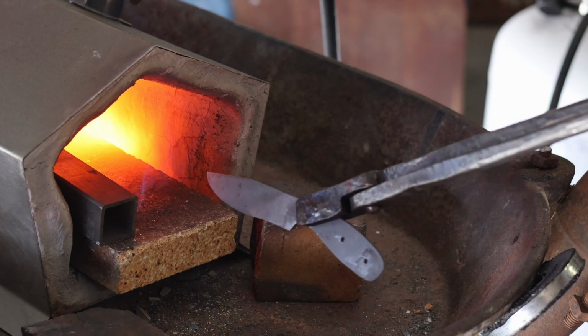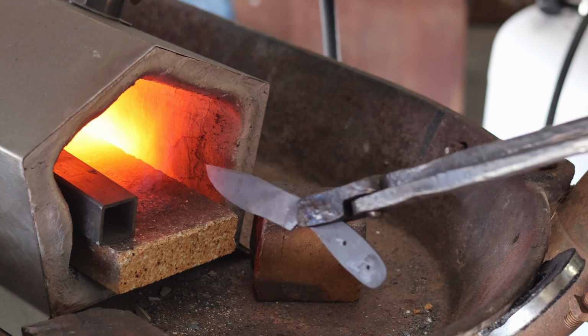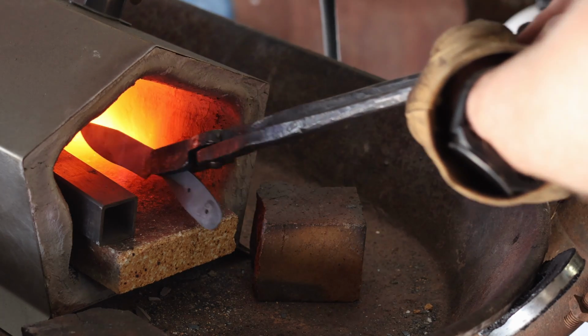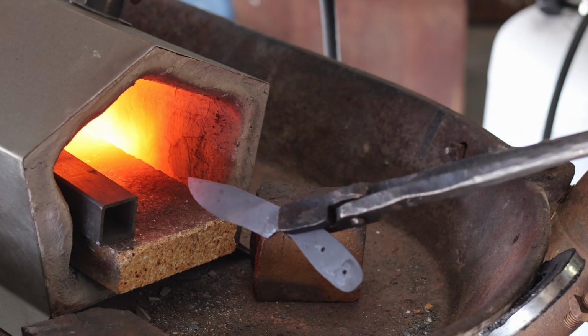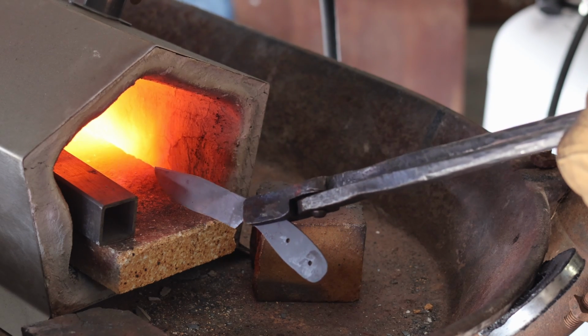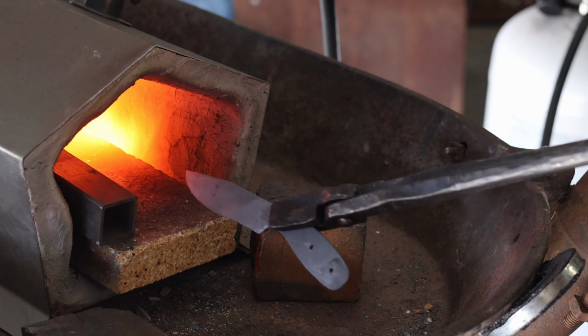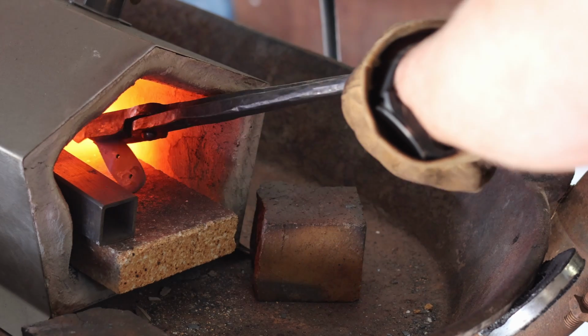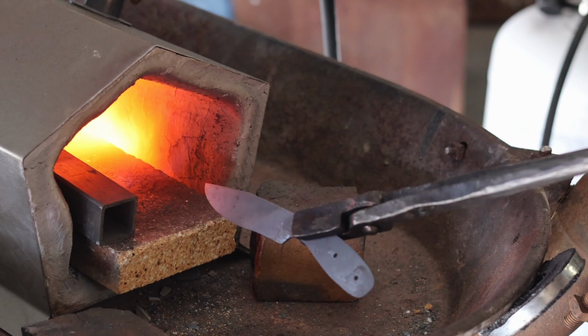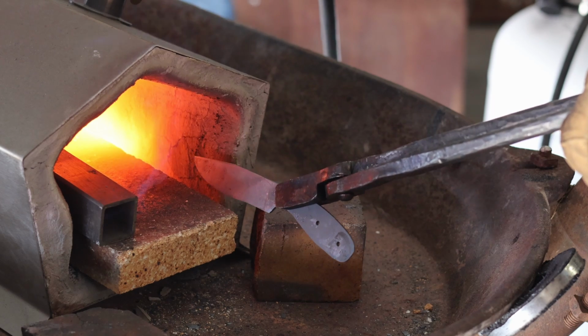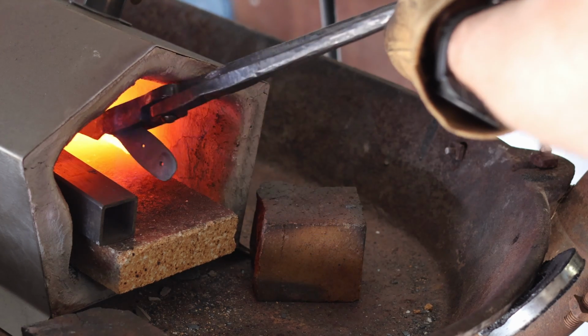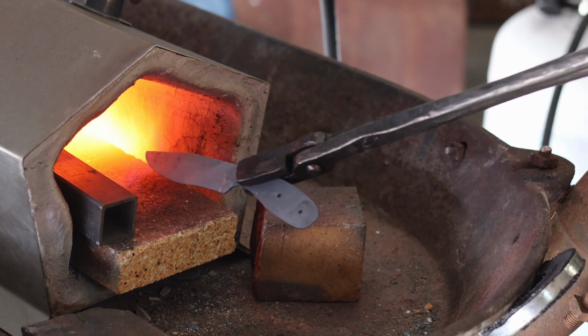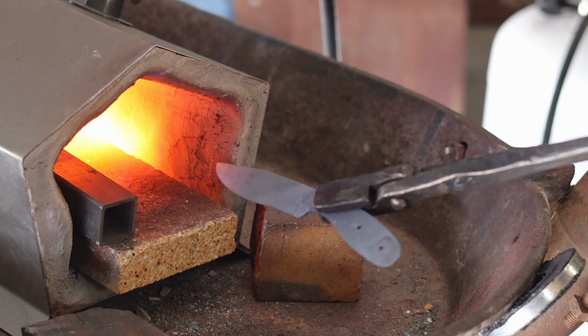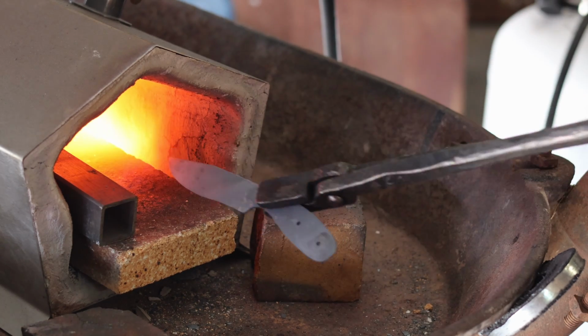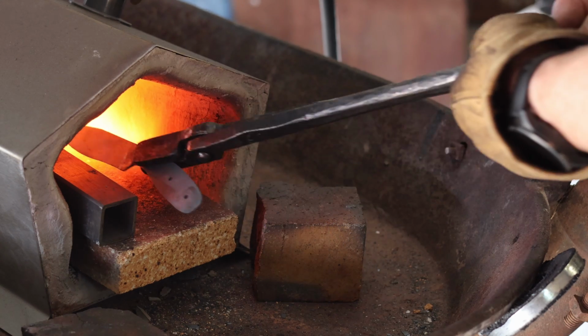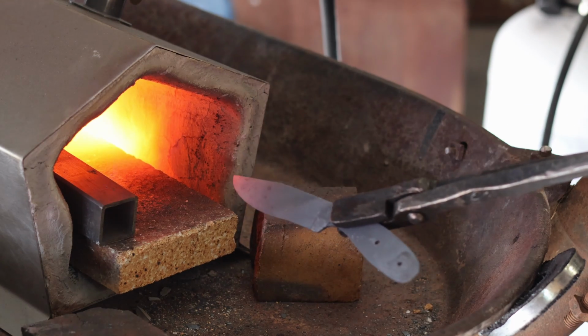Now I've got my tube in there just to, if it strikes my fancy, put it in that and let it kind of soak a little bit. I'm going to run it in and out of the forge. I don't know if you can tell on camera, but the tip is starting to glow. Getting this even along the blade is going to be the biggest challenge, because the tip is not only the thinnest point, but also the point that spends the most time in the heat. So trying not to overheat the tip is one of the critical parts of this process.